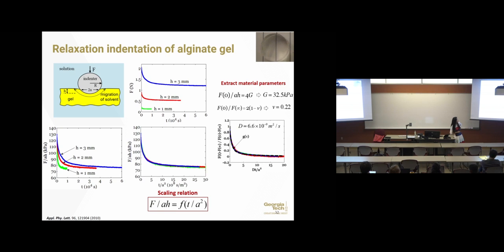Here is the force as a function of time for three different indentation depths. And here I just want to draw your attention that we normalize the force by aH. a is contact radius, H is indentation depth. This is to scale with stress. So put them on the same scale to compare. You can see very clearly for larger indentation size, the relaxation time is longer. So this relaxation time depends on length.